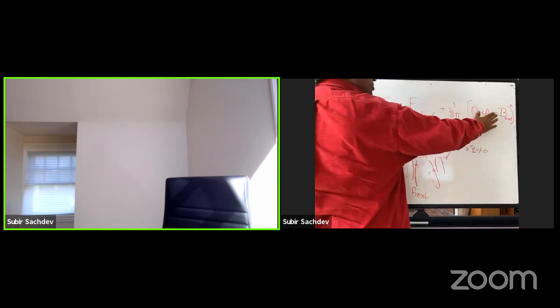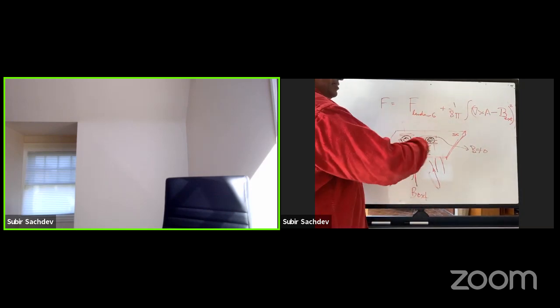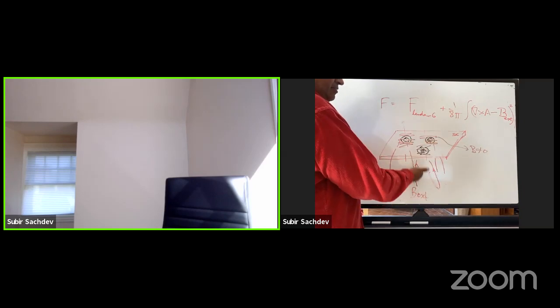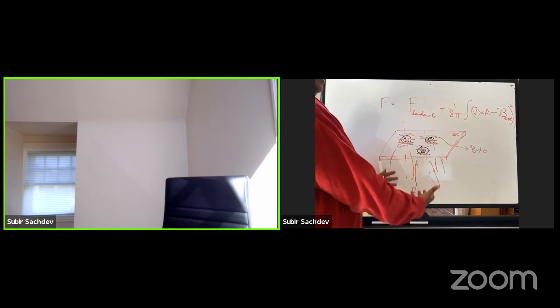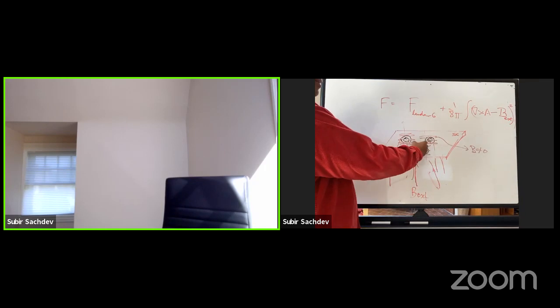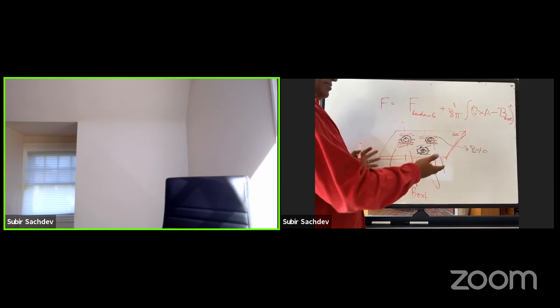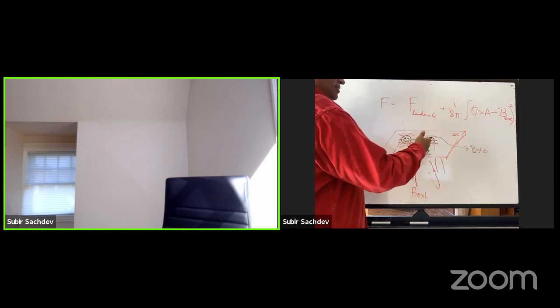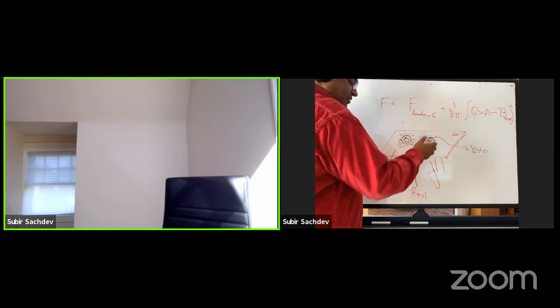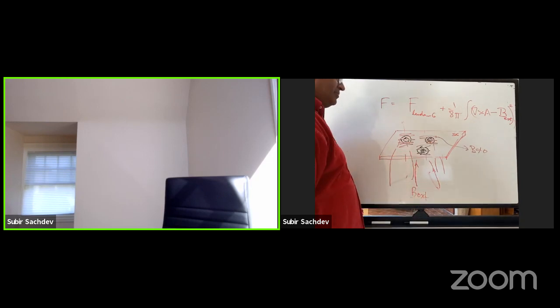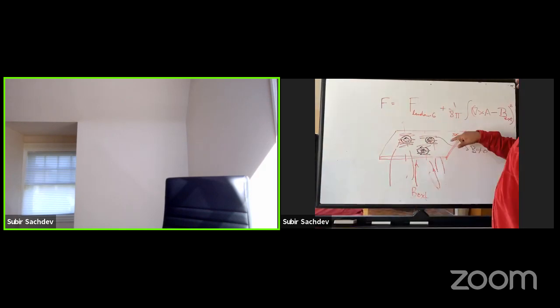And of course, in the end, to make sure this works out right, the density of vortices will be adjusted by the external field, so that, roughly speaking, the external field, which is some uniform field, will split into flux quanta. Each little lump here will carry one flux quantum, and the number of these vortices will be just right so that the density of vortices multiplied by the flux quantum gives you the external field. Okay, and you can then take your STM tip or do some nanoscale mesoscopic measurements of magnetic field and see this lattice.